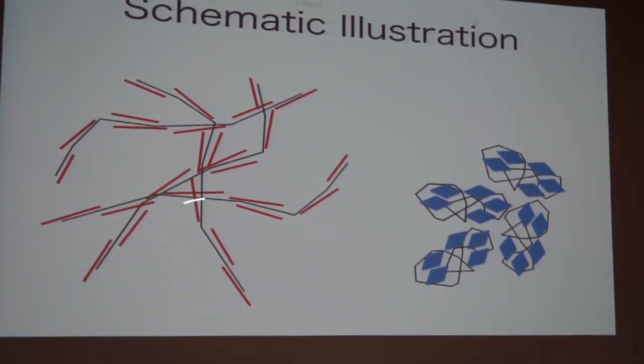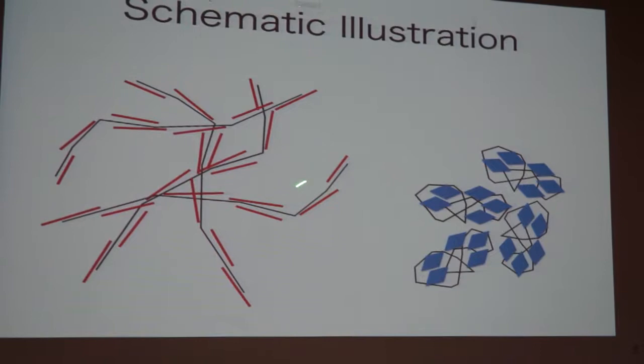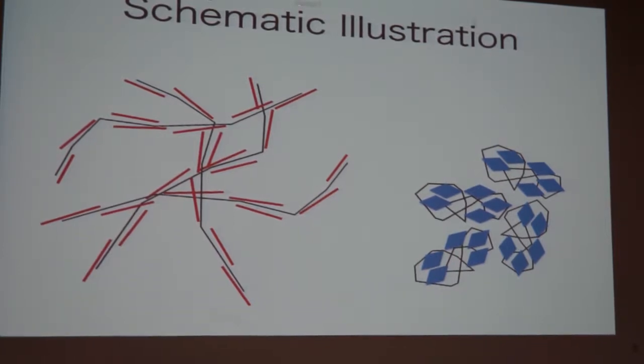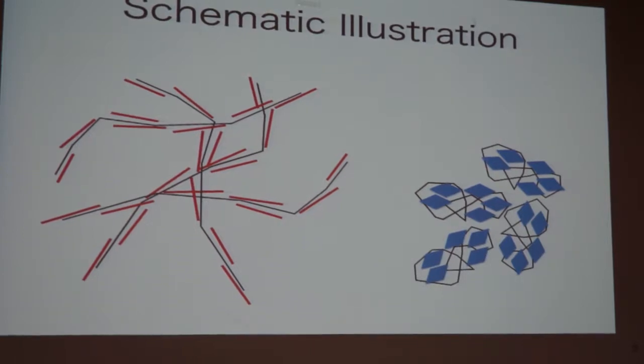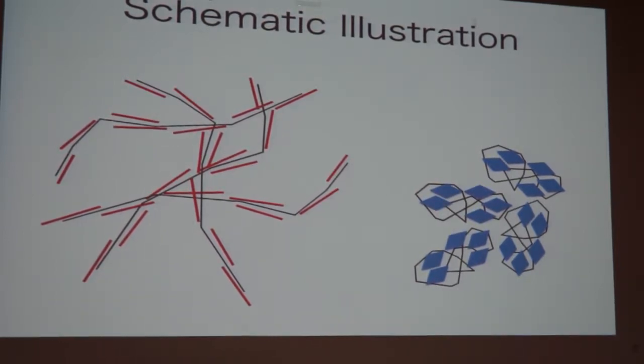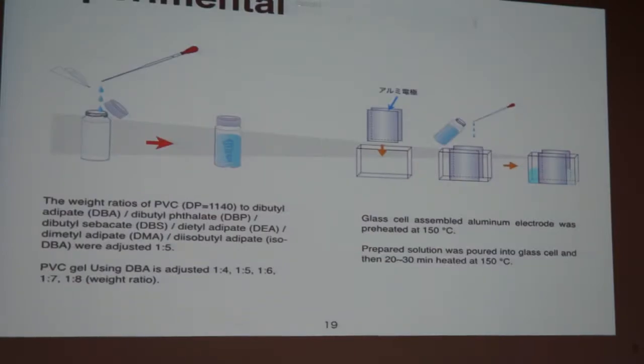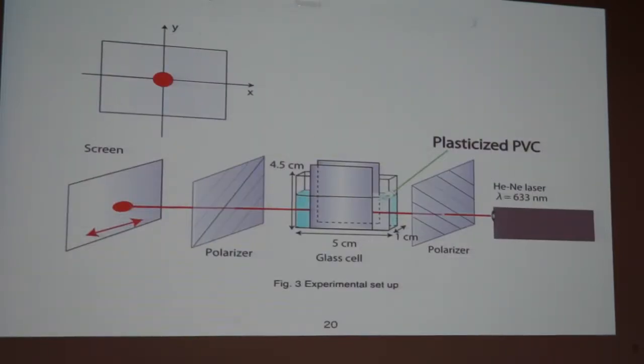In the case of alkane, the linear cluster attached to the polymer has a tendency to extend the polymer chain. But benzene type styrene cluster can lead to some kind of aggregate formation on the chain. That's the difference in physical property. So the aggregate gel can be elongated over 800%. But in this case, only 150% elongation, the gel easily breaks down. The physical property is totally different depending on the cluster.